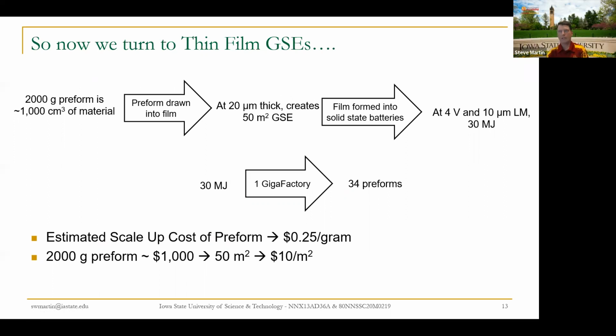Just to do a simple calculation, you've heard a lot perhaps about the gigafactory that Tesla makes. What is a gigafactory? Well, a gigafactory is a gigawatt of batteries. So what does it take for thin films to get a gigawatt of energy? Well, if you take a 2,000 gram, a 2 kilogram preform, that gives you about 1,000 cubic centimeters, about 2 grams per cc. You pull it about 20 microns thick, a little bit thinner than the 40. That gives you about 50 square meters of thin film.